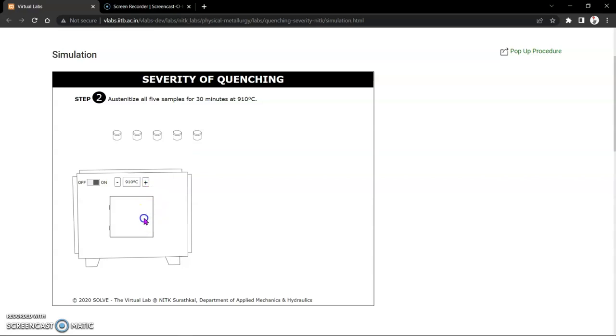Then open the furnace and put the samples in the furnace, all the samples. After that, close the door of the furnace and wait for 30 minutes. After 30 minutes, turn off the furnace.